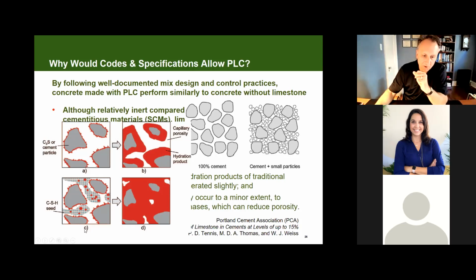Well, if you look at drawings C and D, what's happening there is in between these cement particles, we have these fine limestone particles. So as the glue or the paste starts to be made, those fine limestone particles allow the cement to go further, right? They kind of bridge the gap between cement particles. So you get a better use of your cement glue, if you will. Your cement glue actually goes further because those tiny particles bridge between cement particles and allow you to have a better overall matrix